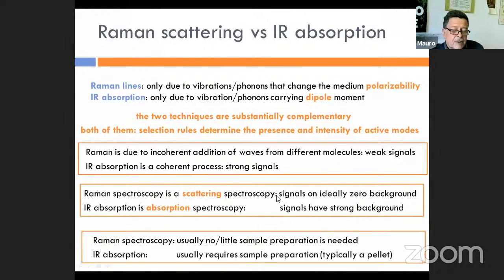Raman spectroscopy is a scattering spectroscopy. So Raman signals are observed on zero background. There is no electromagnetic field at the frequency where we observe the Raman. Instead, IR absorption is seen on the incoming field background. From the practical point of view, Raman spectroscopy usually requires little sample preparation. You can put just your sample under the Raman instrument and see the signal. Instead, IR absorption usually needs preparation of a pellet where the sample is dispersed into an inert salt.